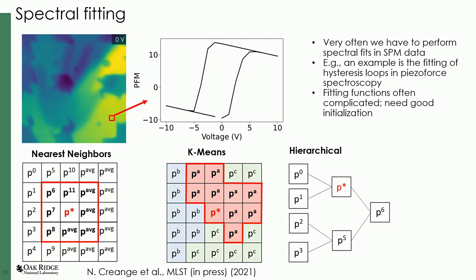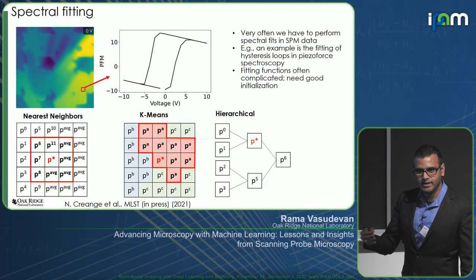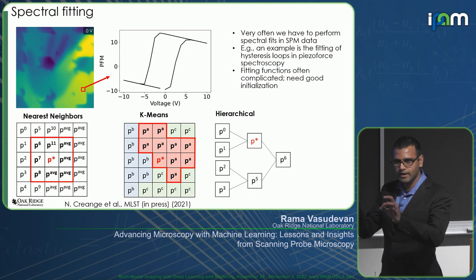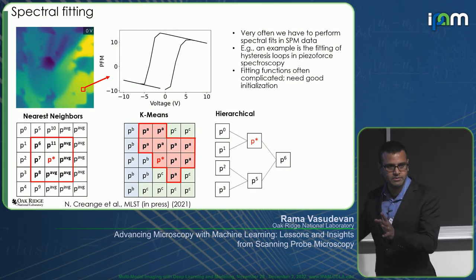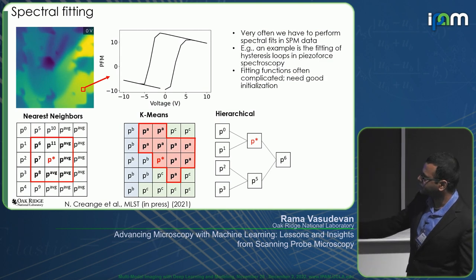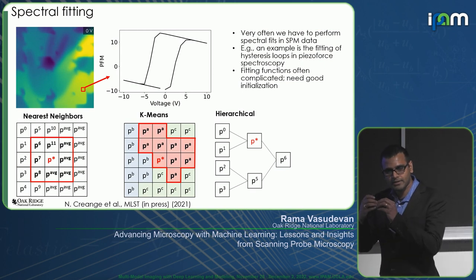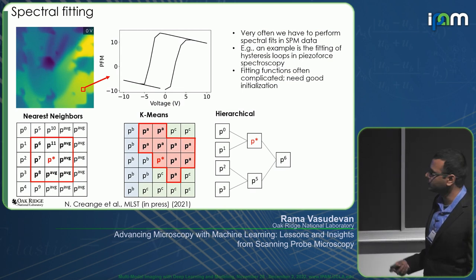There are other ways to get priors for spectra, and the way that we can get better priors is that typically when we collect spectra, we're not collecting just one spectrum at a particular position, right? We're collecting spectra across a dense grid. And so what we typically estimate is that if you are at a particular position and you get a spectrum, then surrounding positions, nearest neighbors, are likely to have very similar spectra, right? So you can do something like nearest neighbor averaging to improve your signal to noise. If we take nearest neighbor averages over our spectra, fit to that particular average spectrum, and propagate the results of that fit to the individual spectra themselves as the priors, that results in slightly improved spectral fits.